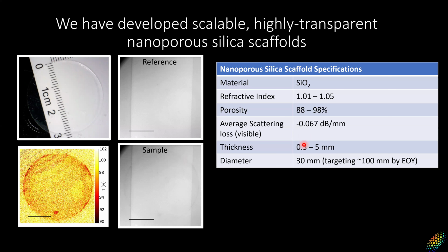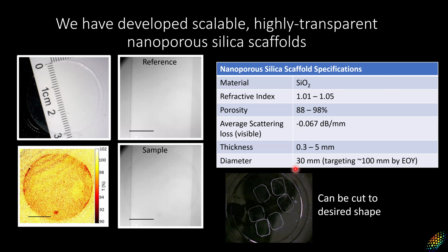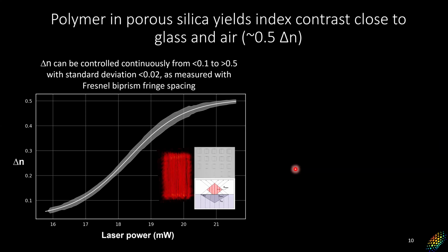And then currently we're making these out to these 30 mm diameter cylinders. But that's mostly a function of the equipment we have. So we have a new piece of equipment coming in that we hope will get us to about 100 mm by the end of this year, and then potentially can scale up from there. And then you can also directly cut these to pretty much any desired shape, either through laser cutting, or we found you can actually directly machine or mill them as well.